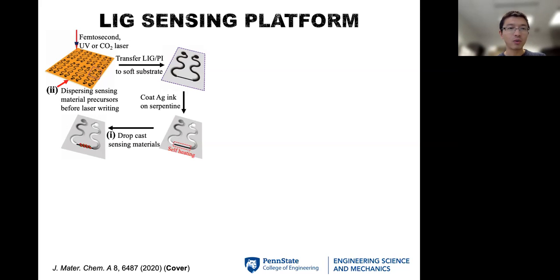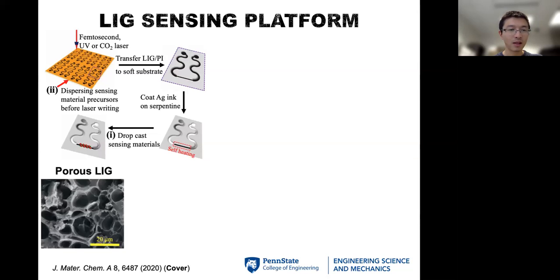So that being said, here we are going after a different approach. It's called the laser-induced graphene. And this graphene-like material is highly porous with a lot of defects. Of course, it's not ideal for the transistor application, but this defect actually provides a huge benefit for us to detect the gas biomarker due to the selective and sensitive detection of the target biomarker.